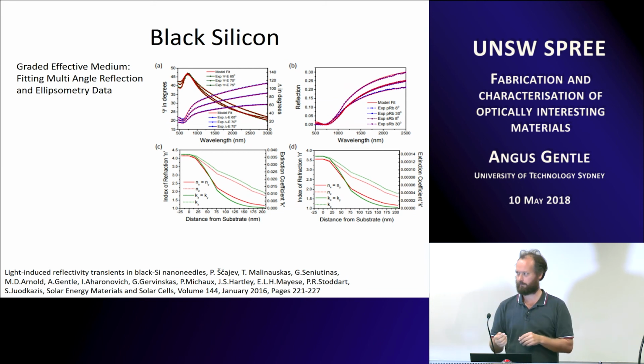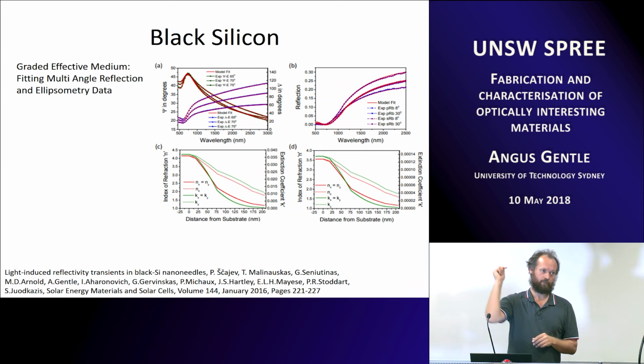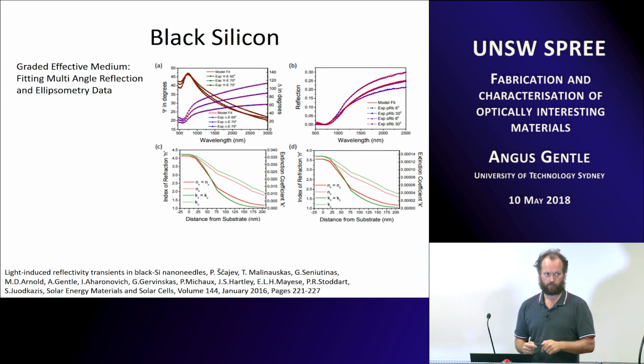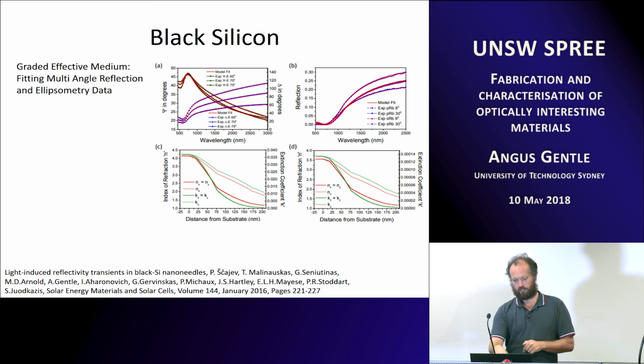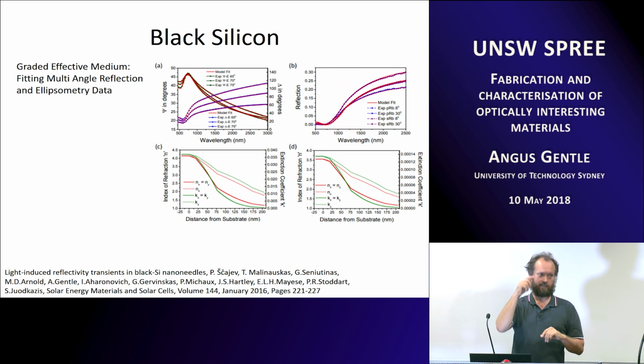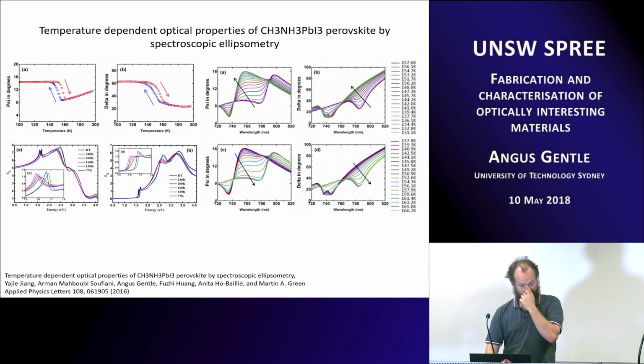So they ended up being a part of their paper where they then did some light-induced reflectivity transients. So they were pulsing it with a very strong laser and then doing pump probe. And so I did those measurements on it. Matt, who's in our group as well, did some looking at, can you model the changes in the reflectance due to temperature effects. So that's basically what ended up looked like, is that the effect they were seeing was due to changes in the temperature of the silicon from the pulse from the probe. It's another one. You'll probably recognize these names down the bottom.